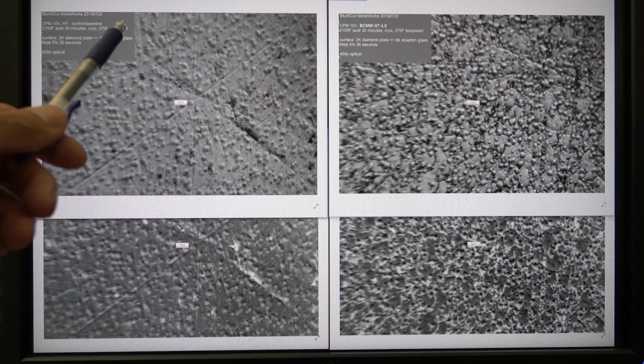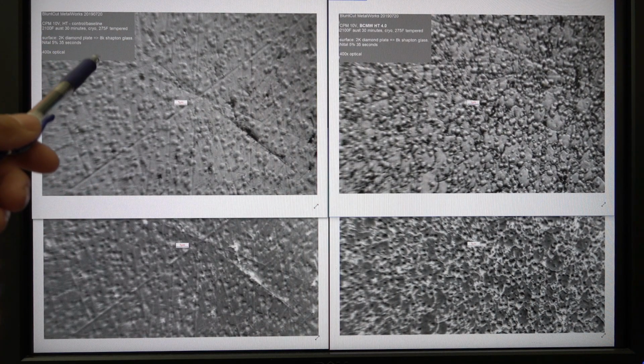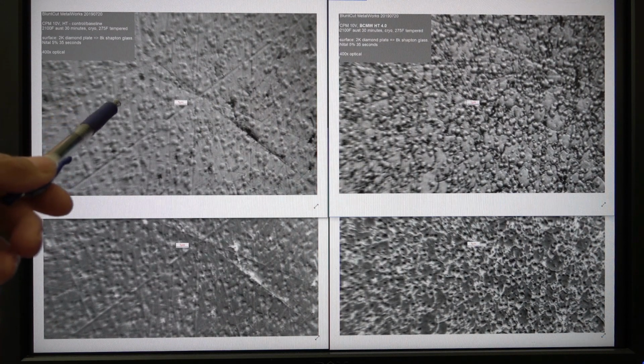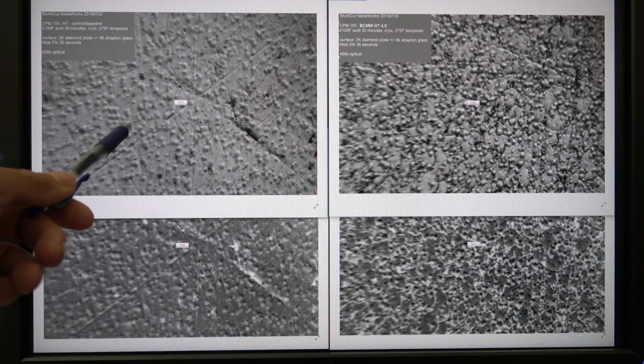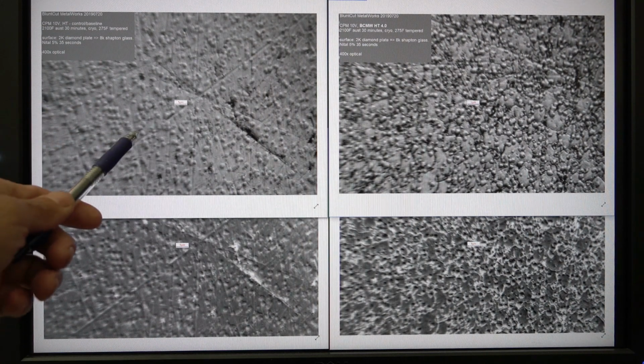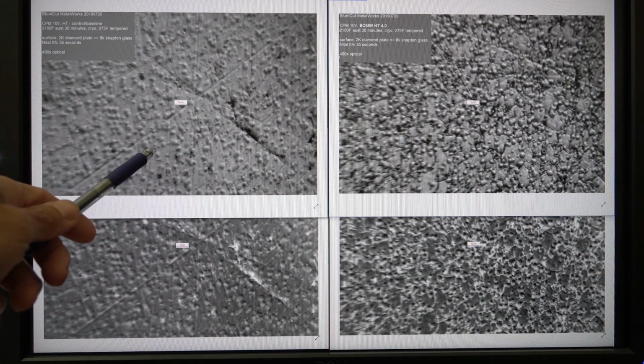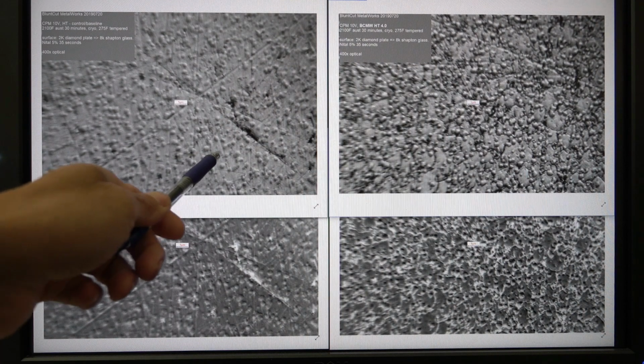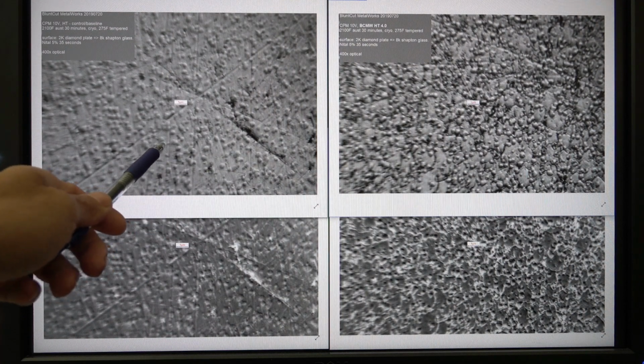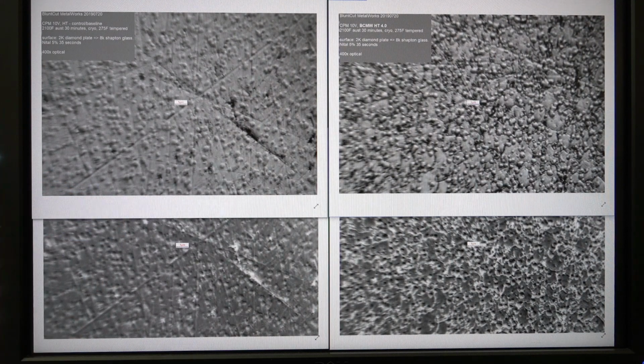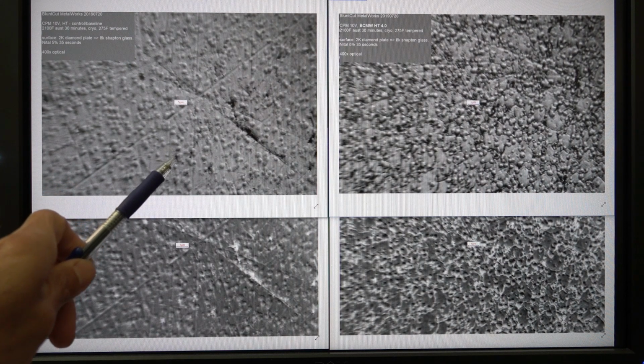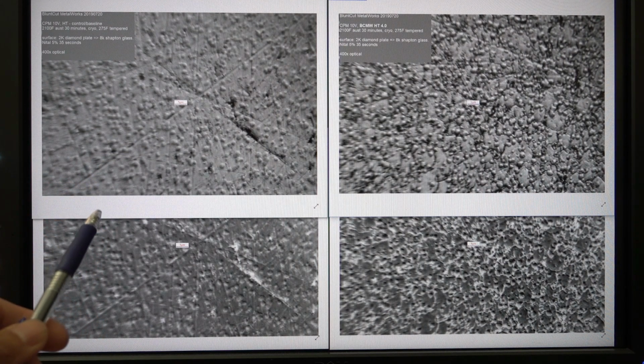Now, this is the control, meaning that we are using the standard heat treat recommended by the manufacturer of CPM 10V. And as you can see, each of these lumps is a carbide. Here the flat part is the matrix, literally flat. The bumps are partially exposed carbide on the surface. And down here is the inverted version of up here.